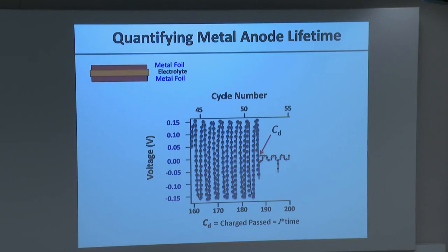An oscillatory response where the amplitude of the current remains more or less the same, okay? What we observe in general is that this kind of Ohm's law-like response sustains for some number of cycles, in this example for about 55 plate strip cycles, but then it reaches a point where something gives. And we have a sudden drop in the voltage, meaning that there's a lower resistance pathway somewhere, and this is a dendrite, this is the short, indicating that you can quantify very easily the effectiveness of this membrane, either based on the amount of charge passed, CD, at the time the dendrites are formed, or by the number of cycles at which they're formed. Now, we like this number better because CD would be infinite in the case of something that stops the dendrites entirely, such that its reciprocal would be zero. So this gives us a really simple figure of merit to know whether this theory is right and whether the materials we've developed are effective.